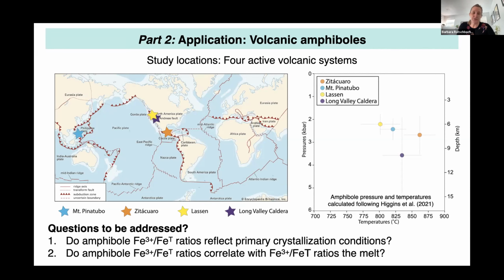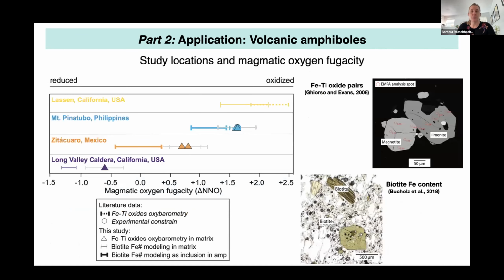So the questions we can now address for those 4 localities is, do the amphibole ferric over total iron ratios reflect primarily crystallization conditions? So do they reflect the conditions they encountered while crystallizing from an oxidized or reduced magma? Or are there any processes which happen after crystallization of the amphibole which potentially modify the ferric over total iron ratios? And if we show that we're actually looking at magmatic ferric over total iron ratios, we can then pose the question whether those ratios correlate with ferric over total iron ratios in the melt. So the first step we did is to look at the study locations and determine the magmatic oxygen fugacity of the melt. That basically means how oxidized or reduced were the magmas which crystallized amphiboles.